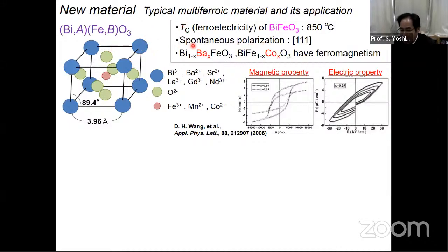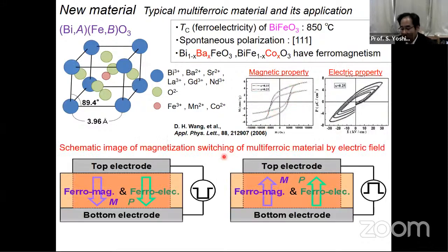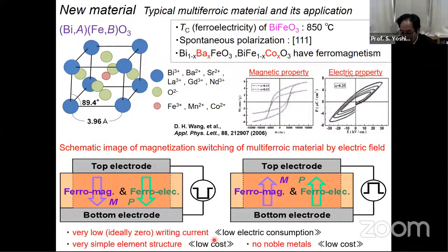The important thing is the properties of magnetism and electricity. BiFeO3 has ferroelectricity and ferromagnetism. And if we substitute the material like this, we can generate ferromagnetism like this. If the interaction between magnetic moment and polarity is strong, we can switch the magnetization direction by applying a voltage. In this system, there are many merits for reversal of the magnetization direction.